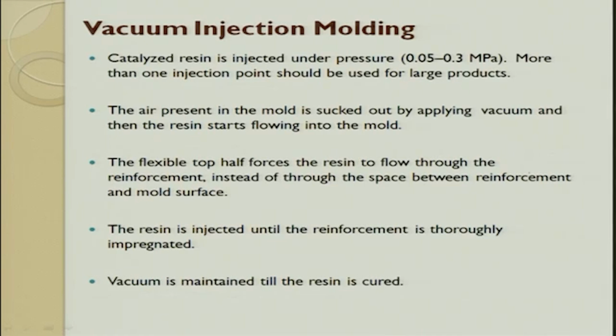So, the catalyzed resin is injected under a pressure of, what is catalyzed? Catalysis, the catalyst is nothing but to accelerate the reaction. Catalyzed resin is injected at a pressure of 0.3 megapascals. More than one injection point can also be used if you want to make a large component.